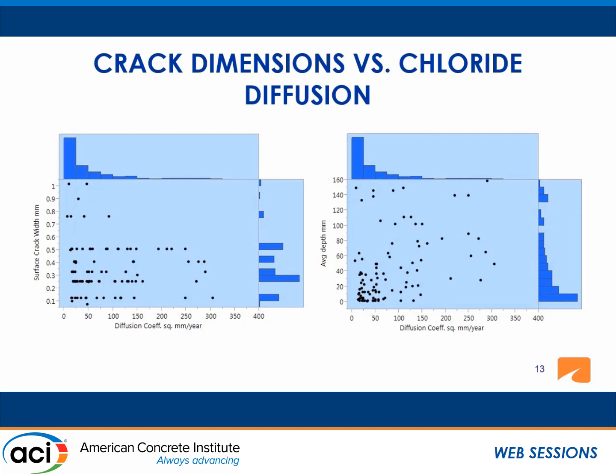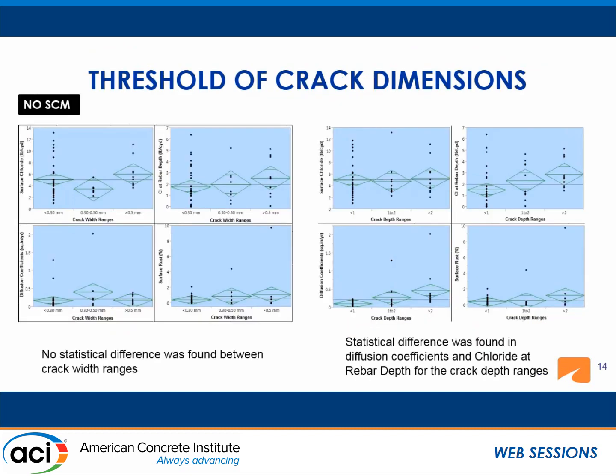But on the other hand, on the right side, we have the correlation between the diffusion coefficients and the crack depths. And as you can see on the distributions, the histograms on the top and the bottom, they had much more correlation than the surface crack widths. And we wanted to divide the crack width and crack depth data into ranges, so that we could see if there's any statistical significance going on.